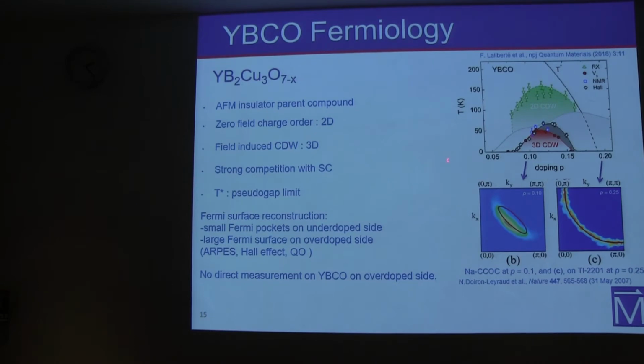So this is a current phase diagram of YBCO, so temperature versus doping. Most of the work on YBCO has been done with doping and not with pressure. You see here in gray the superconducting dome, with a very peculiar shape of this shoulder that intrigued the scientists for a good 15 years, and then eventually they discovered that there is a 2D charge density wave that's competing or collaborating, it's still debated, with the superconducting dome.